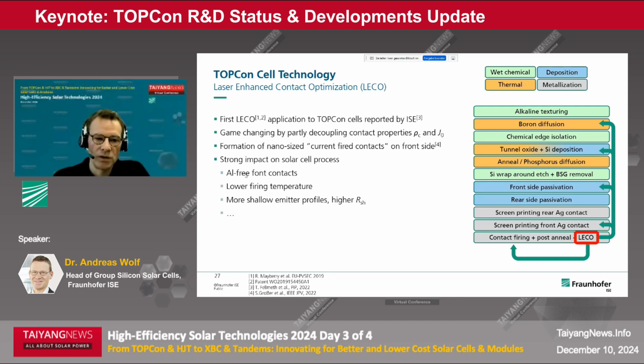For example, it enabled the use of aluminum-free pastes, much lower firing temperatures, and then in turn also very different boron diffusion parameters with a more shallow profile, which allowed lower diffusion temperatures, more cost-effective processes here, higher throughput, and also higher sheet resistance, increasing implied VOC values.